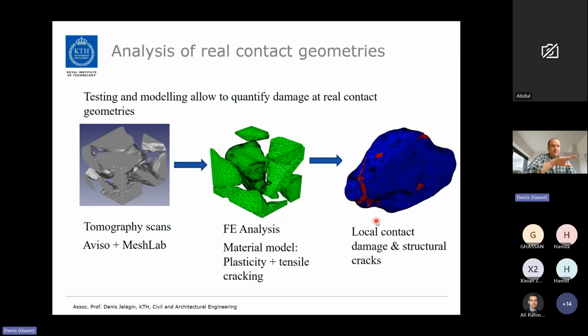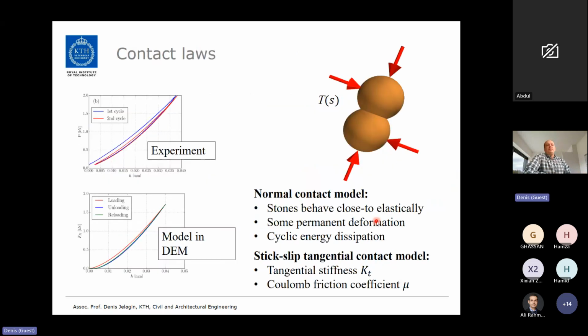So basically, combining those indentation experiments and the finite element modeling allows us to come up with particle damage laws, which are generalized for arbitrary particle geometries. So in spite of the fact that in many of our simulations we use spherical particles, they deform and fracture in the way irregular particles will deform and fracture. So this is how the contact law we proposed for discrete element simulation looks. Here on top you have experimental results, and at the bottom you have our proposed contact law. We capture dissipation during the first cycle, so pretty much the only experimental finding we ignore is dissipation during the second cycle.